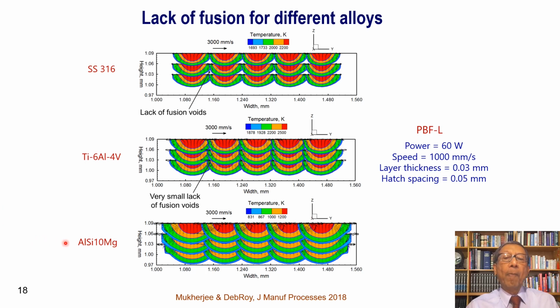And so in case of stainless steel 316, for these processing conditions, there is going to be lack of fusion defects, and in case of aluminum silicon 10 magnesium alloy, there is not going to be any lack of fusion defects.